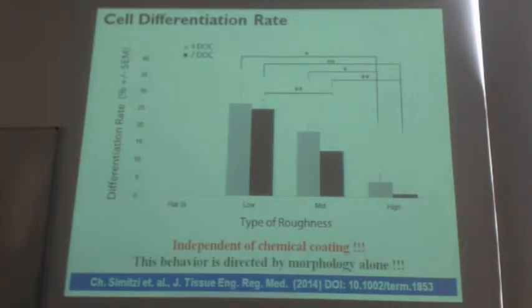Here you can see the differentiation rate, the percentage of cells that are differentiated, as a function of the type of roughness, and you can see that in the low and mid roughnesses, cell differentiation is observed. But this is not the case in high roughness. So despite the presence of nerve growth factor, we have no differentiation of PC12 cells. And this behavior is directed by the substrate morphology alone.